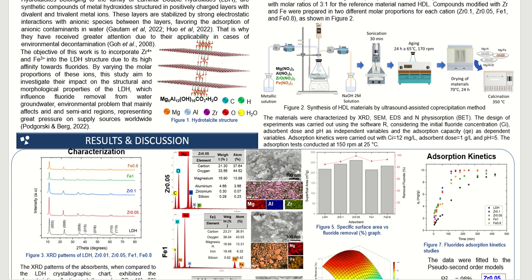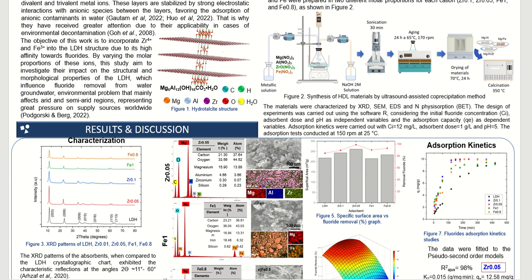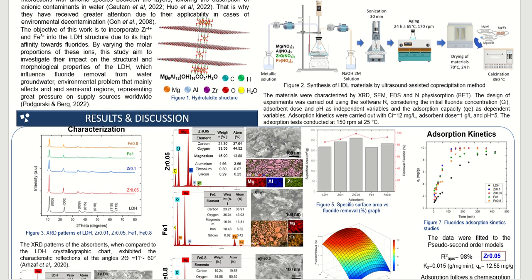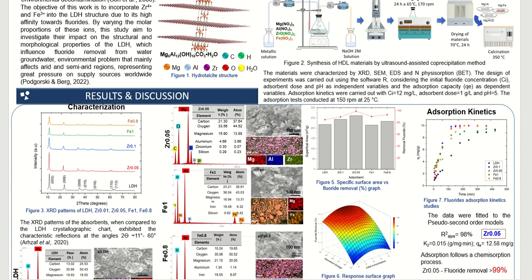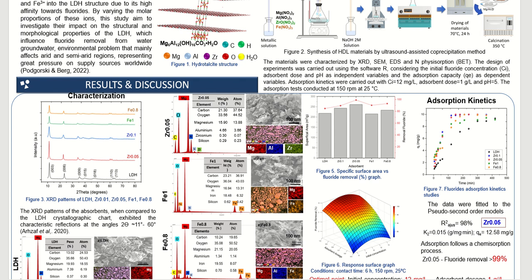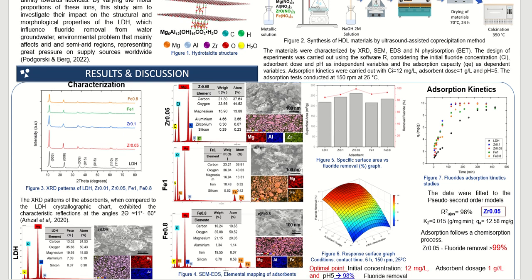The structural, morphological, and physicochemical characteristics were observed by means of X-ray diffraction, energy dispersive X-ray spectroscopy coupled with scanning electron microscopy, and nitrogen physisorption, which, using the Brunauer-Emmett-Teller method, gives the specific surface area of each material. Then, the adsorption process was studied through preliminary tests. A design of experiments was carried out using the response surface method and adsorption kinetics.